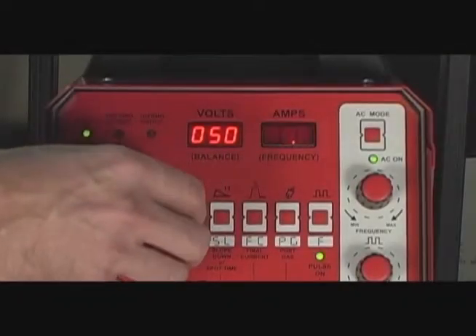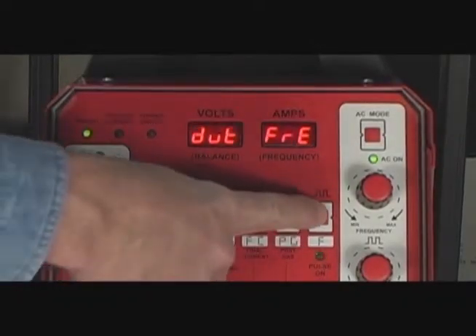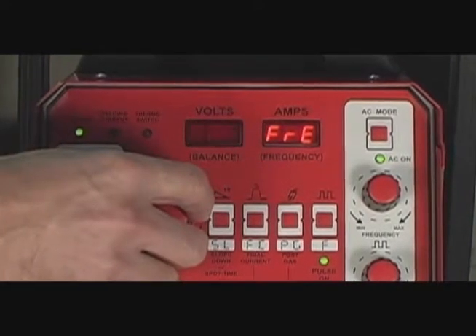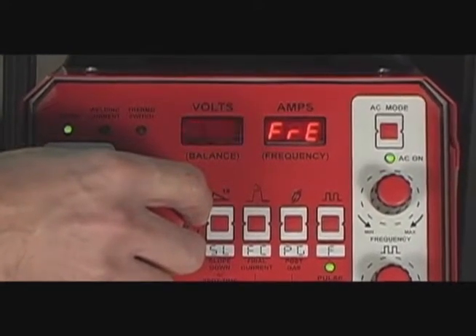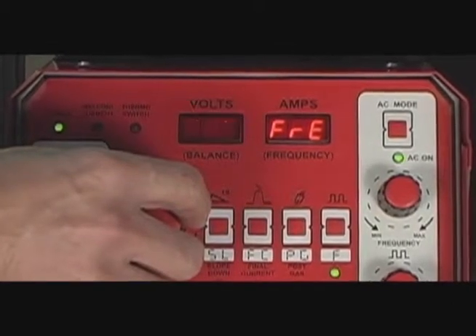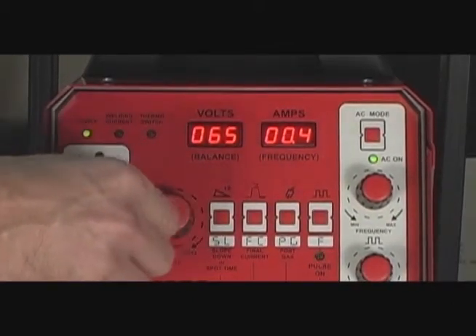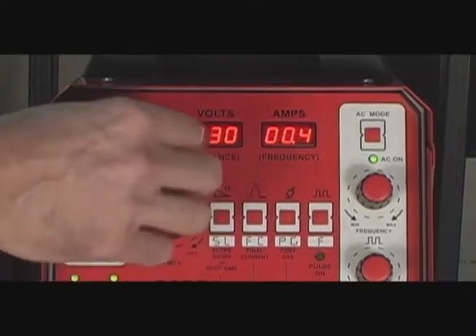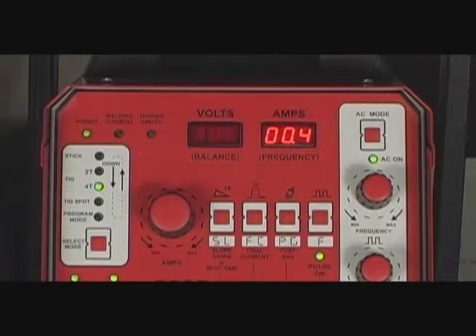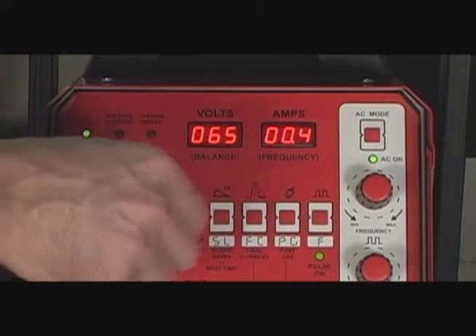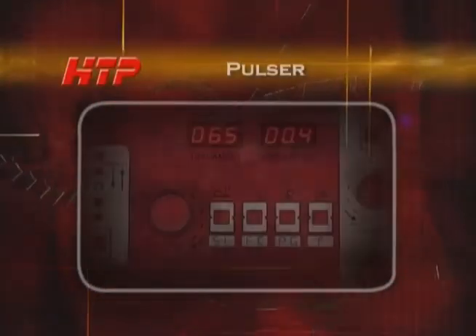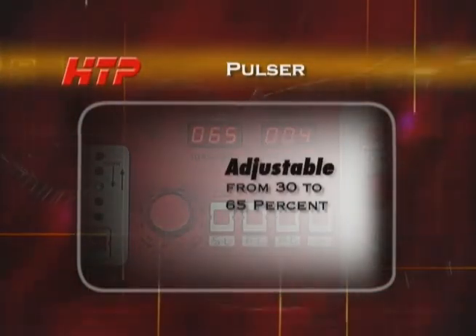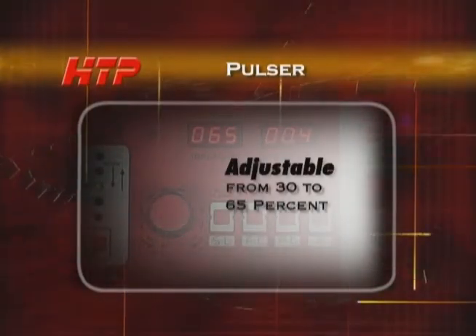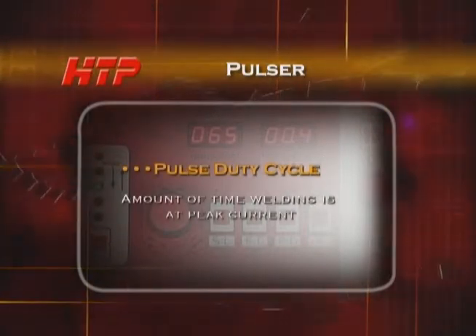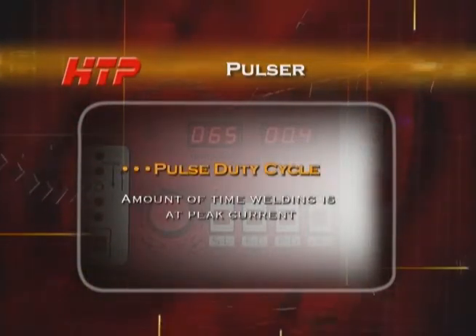To adjust the pulse duty cycle, depress and release the pulse on button until DUT, which is displayed in the volts display, is flashing. When the display is flashing, adjust the amps knob to set the pulse duty cycle. Once the amps knob is turned, the display will change from DUT to display the duty cycle in percent. The duty cycle can be adjusted from 30% to 65% in increments of 5%. Again, the duty cycle is the amount of time the pulse is at peak current.